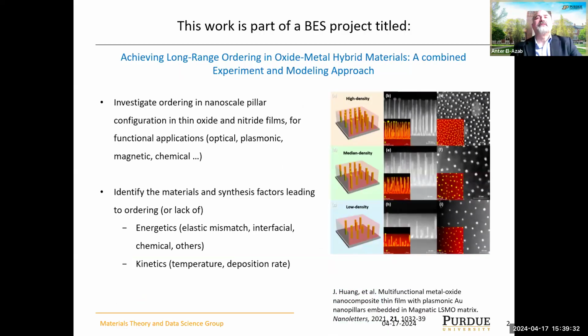This research is part of a project called Achieving Long-Range Order in Oxide Metal Hybrid Materials. As the title says, we're trying to design these materials in such a way that they have a film configuration, but the film is traversed by these thin pillars, nano pillars. We call them pillars. They used to be called whiskers a long time ago, but they are of nano dimensions, a few nanometer diameters, like 3-4 nanometers. They are self-assembled in the sense that they grow by just depositing the atoms. And the organization of these does have an influence on the properties. The properties of interest are optical properties, plasmonics, magnetic, and catalysis applications as well.